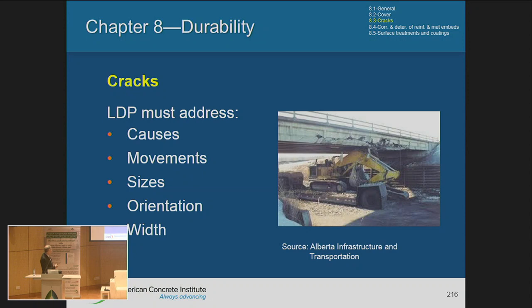Looking at cracks. There are different types of cracks. We have to look at their causes. Why did they occur? Is it because of shrinkage, temperature cracks, or are they structural cracks due to loading or settlement? Are they active or dormant? What's the size, orientation, the width? All that will tell me. If they're straight up, they may not be as critical as if they are inclined, especially at the support, or if you see cracks around the column versus cracks away from the column in the midspan. Those are issues that the engineer has to look at and evaluate.